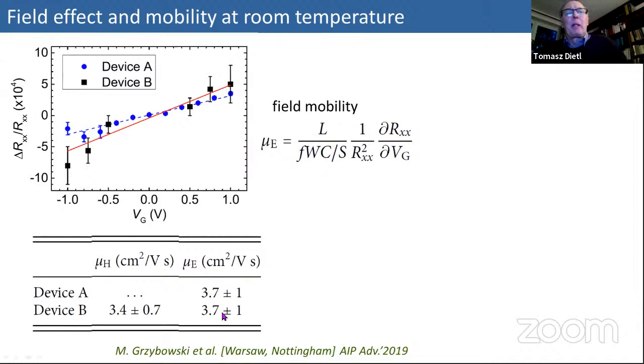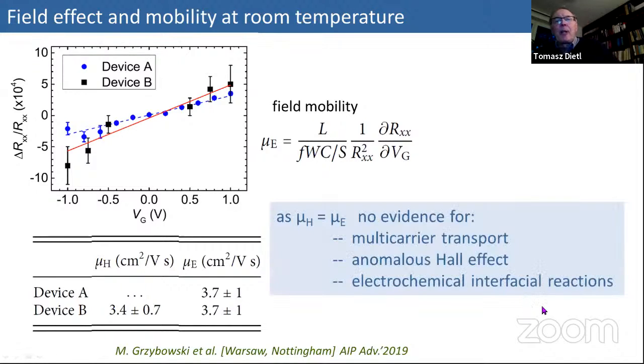Now, probably some of you who are familiar with semiconductor physics know it's kind of standard that by measuring field effect in materials, you can determine mobility. In this whole structure, he was able to compare this field effect mobility with the Hall mobility, and found actually very good agreement: the Hall mobility measured by Hall effect is very similar, within experimental error, to this field mobility. He was able to draw several conclusions from that. Namely, that if multi-carrier transport is present here, it's not very important, because otherwise you would not get this agreement. Also, the anomalous Hall effect induced by field must be small because this would affect Hall mobility. And also that there is no electrochemical interfacial reaction, that this change of resistivity is not due to electrochemistry, but due to change of carrier density.